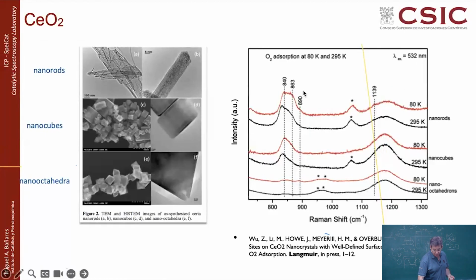And here, for instance, you can observe how the adsorption of oxygen doesn't result in the same kind of species. This is work made by Zili Wu and Steve Overbury from Oak Ridge National Lab about how you get these peroxide species, and it's not the same depending on the temperature, on nanorods or on nanocubes or nano-octahedra. So in nano-octahedra, for instance, you don't get the peroxide species. You do get some of them on the nanocubes, which have some reactivity, and on nanorods, which have more reactivity. So these things already happen by shaping how you make the ceria nanoparticles.